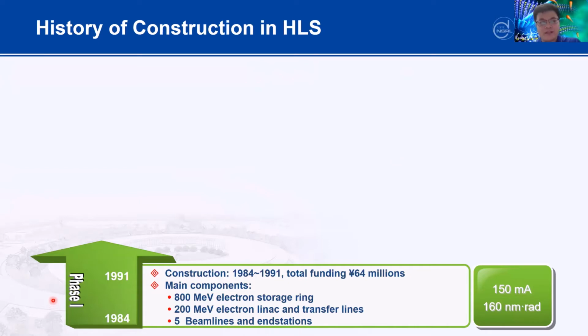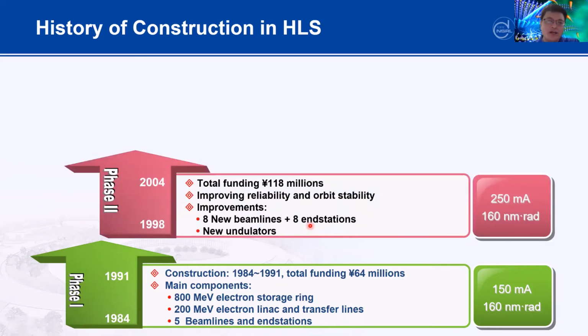The first phase was from 1984 to 1991. This was the first construction, and the total funding was about 64 million. The main components were the 800 MeV electron storage ring and the 200 MeV electron linac and transfer line. At that time, we had 5 beamlines and endstations. Then we went to the phase 2 construction, with total funding of about 118 million. In that phase 2, we tried to improve the reliability and orbit stability. And at that time, we reached about 16 endstations and with a new undulator.